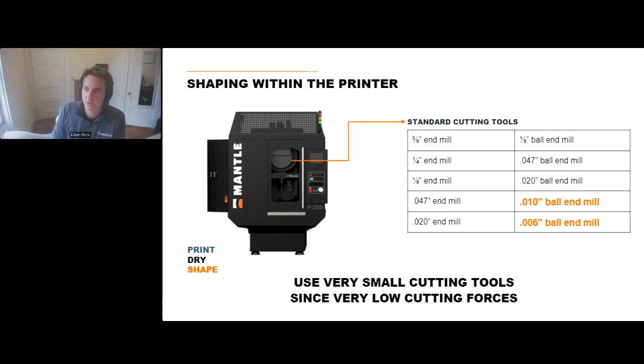One thing I wanted to point out, that is pretty interesting about this, is that since we are machining essentially a dense foam and we're machining layer by layer, we're able to use some really small cutting tools. So we're actually just using standard cutting tools. There's a turret inside of the machine, so we can use a variety of different tools at once. But we're able to use tools as small as a 10th thou and a 6th thou ball end mill. These enable really crisp feature details and really sharp small features to be produced here.